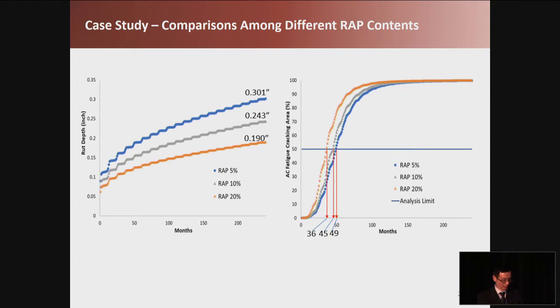Okay. So here is the TexasME prediction. This is the rut depth. At the end of 20 years, there's a different rut depth. So basically, if you have higher RAP, you will have a lower rut depth, and then also you will have less cracking life. Here, 50% fatigue cracking is used as the failure criterion. So here it is 36 months to failure. That's the fatigue cracking life. So basically, with higher RAP, you will have less cracking life, but less rut depth.